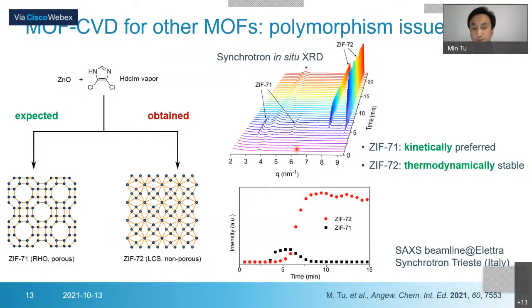And if we integrate the peaks, then we can see the reaction profile here. Firstly we form ZIF-71, and it disappears. Then we form ZIF-72. So we propose that ZIF-71, this porous structure, is kinetically preferred, and ZIF-72 is thermodynamically stable. As the reaction goes on, ZIF-71 can convert to ZIF-72.